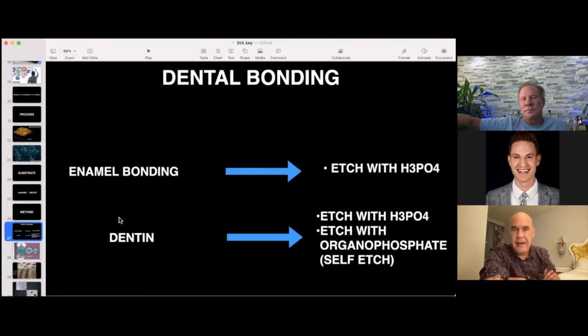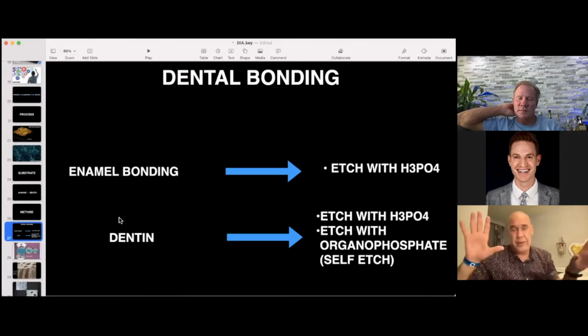It worked fine. And other companies jumped on board and tried to compete. Their self-etch products were not very good. They were too hydrophilic. They were very acidic, too much water content. The adhesive layer was degraded by the presence of water in dentin. Bond strength was not very good. All these things were happening. And what happened was that it generated a really bad reputation for self-etch.